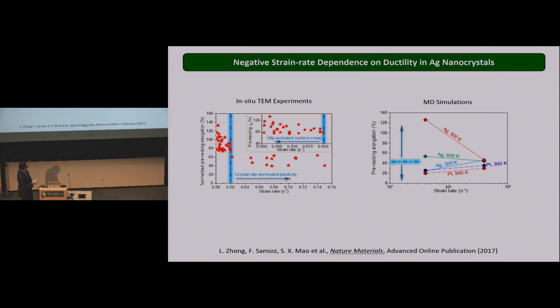And so when we did the simulation, we observed exactly the same phenomenon, which is when we allow for surface diffusion, there is clearly an inverse dependence, a negative dependence. When we stop surface diffusion by decreasing the temperature or use platinum, then we have the standard dependence. So that shows clearly there is an interplay between the plasticity and the surface diffusion.